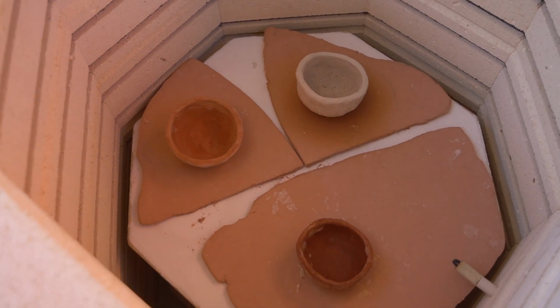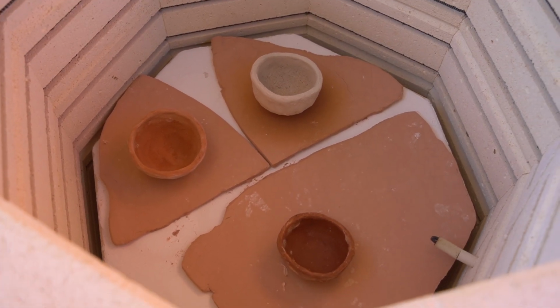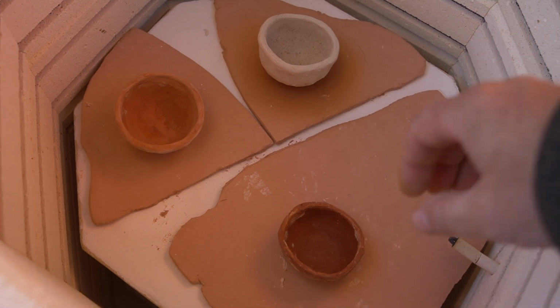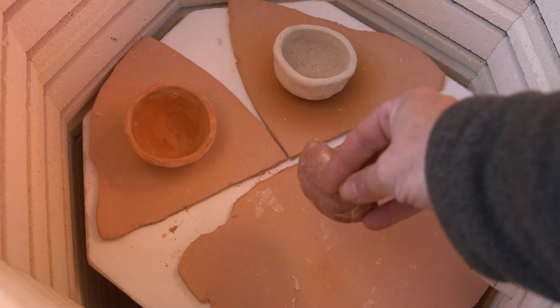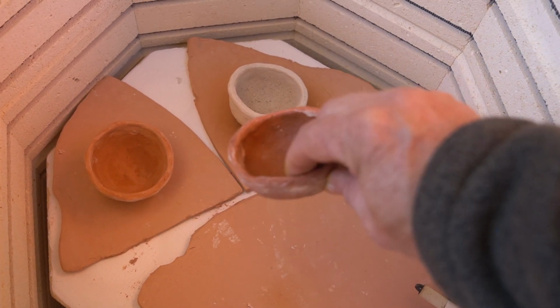So I went home, I came back here this morning and we opened the kiln and here's what we found. This kiln fired up to about 2000 degrees Fahrenheit, or about 1100 degrees Celsius, something like that. And everything came through fine.